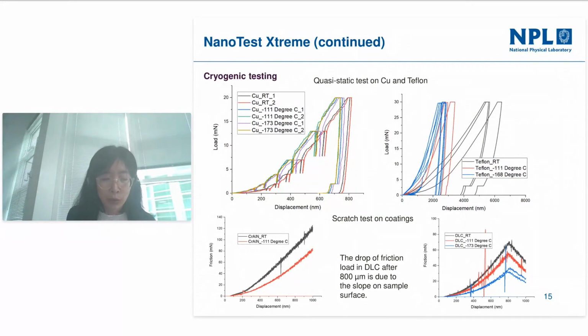and the latter gives a much more severe change of the property with the temperature, while as you can see in the copper, it has relatively higher thermal drift, and the mechanical properties increase with reduced temperature. We found that performing the measurement on reference materials and cross-validation is helpful to interpret the results, in particular at extreme conditions, which can be affected by both thermal drift and frame compliance from temperature changes.